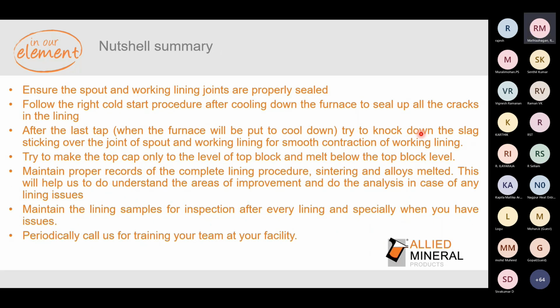Normally, whenever you shut down and restart it, ensure the joint between the spout and the working lining is good enough. If you find any small cracks, you can just clean it up, make a V notch, and put the plastic refractory again and seal it up to avoid any metal penetration through that particular joint. Follow the right cold start procedure after cooling down the furnace to seal up all the cracks and to avoid finning.